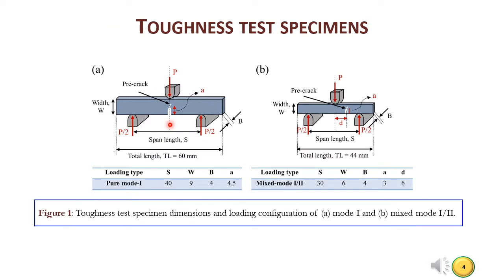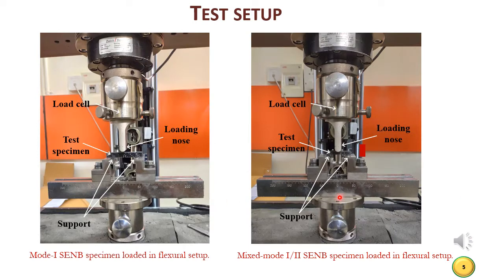Figure 1a shows pre-cracked single-edge notched bend specimen for mode 1 case. Here the pre-crack is present at the center. Figure 1b shows pre-cracked specimen for mixed mode case. Here the pre-crack is present at an offset distance from the center, thus causing asymmetric loading on the specimen. The picture shows the 3-point bending machine used for the toughness test. The pre-cracked SENB specimen is supported at both ends and loaded at the center.